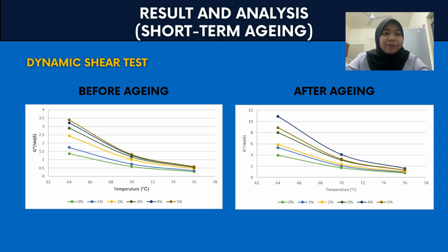After aging at 64 degrees Celsius, the control binder had a slightly lower value than the modified binder, resulting in lower resistance to rutting. However, at all other temperatures, the control binder also had a lower value of G star over sin delta. The sample with 4% synthetic hard wax after short-term aging shows the greatest value of G star over sin delta at lower temperature, becoming stiffer, while the traditional binder shows less change.